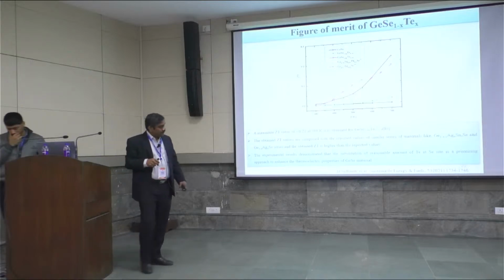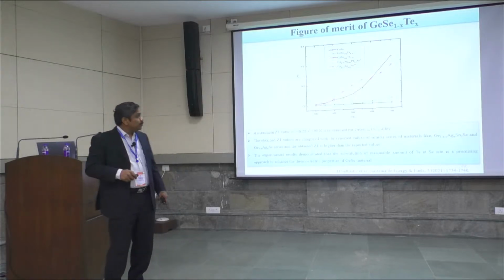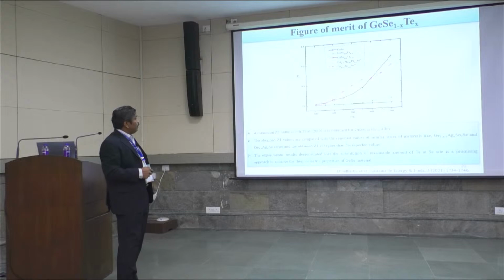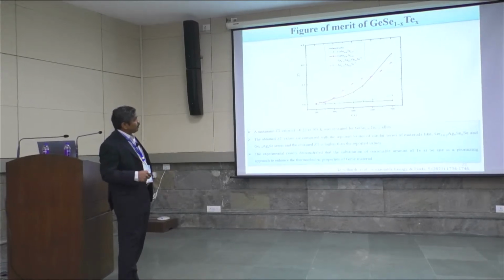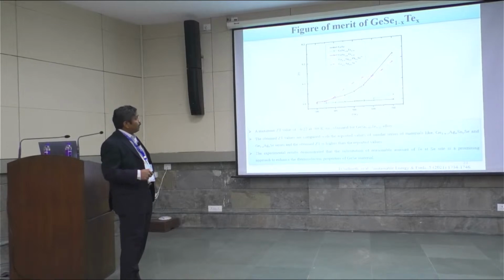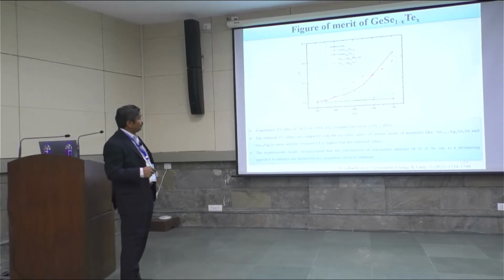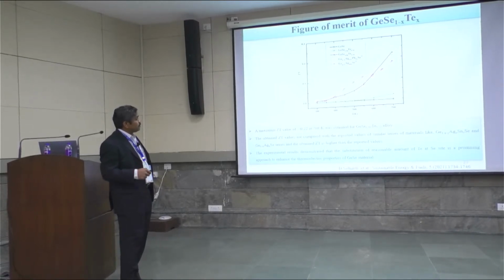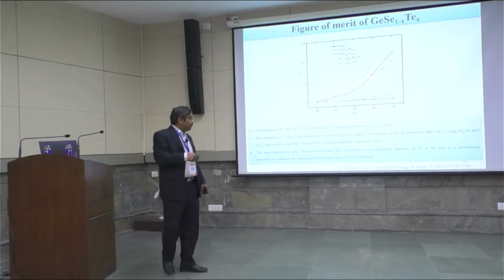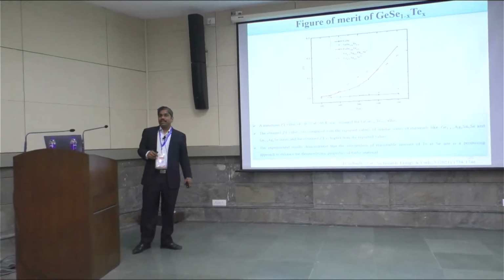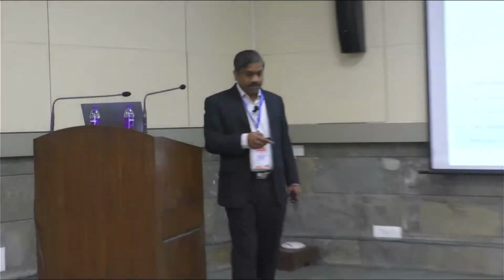Okay, so this is the ZT, the figure of merit of this tellurium substituted germanium selenide, and the 20% tellurium substituted sample shows a relatively high figure of merit compared to the rest of the samples, and that is also relatively higher than that of similar reported systems. So this work shows that the substitution of tellurium is quite beneficial for improving the performance of the systems. And similarly, we tried the copper substitution at the germanium site instead of the selenium site.